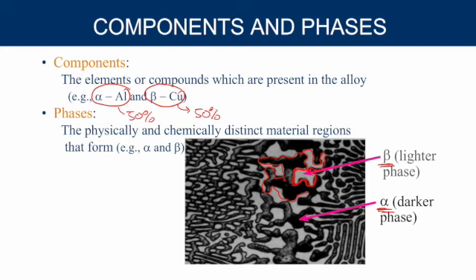And then typically, in phase diagrams, we will use Greek letters as shortcuts for the two materials. So alpha, beta, gamma, delta, all of these are used quite a bit because most alloys have multiple phases, and we define those by the Greek letters. But they typically correspond to one of the fractions of material. So alpha might mean mostly aluminum, beta might mean mostly copper, and then something like gamma might mean a combination of aluminum and copper if it's a multiple phase region. So we'll go into that as we go along, but we need to understand the Greek letters because it helps us define the phase regions that we see in our graphs.